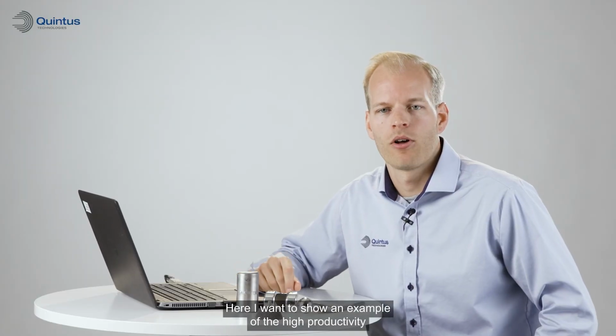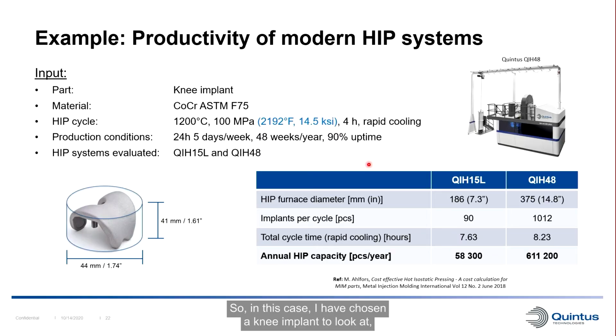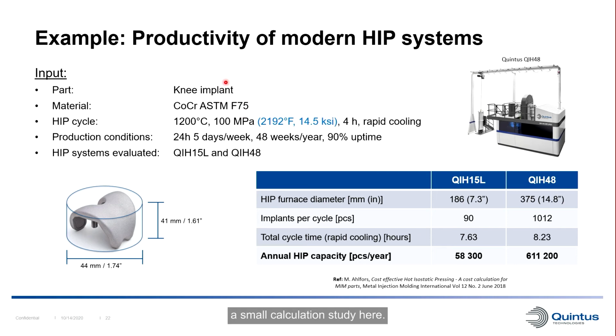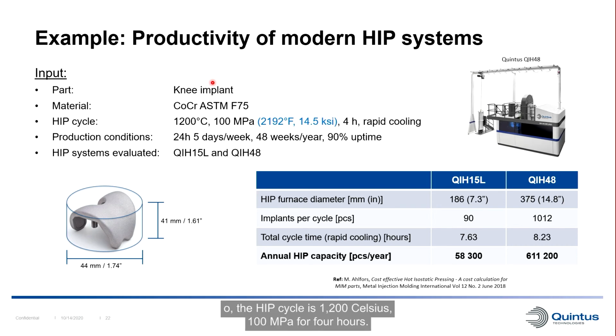Here I want to show an example of the high productivity of these modern HIP systems today. So in this case, I have chosen a knee implant to look at, a small calculation study here. Material is the cobalt chrome F75 alloy, so the HIP cycle is 1200 Celsius, 100 megapascal for 4 hours. The production conditions I've assumed to be 24 hours per day, 5 days a week, 48 weeks per year, and with 90% uptime of our HIP system. Then I looked at 2 different products of ours, the QIH15L and the QIH48.